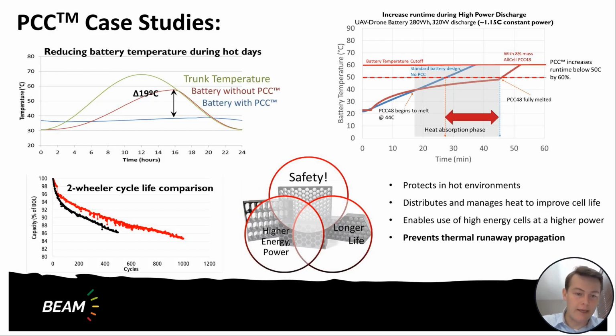We also look at a cycle life improvement of the PCC for a specific two-wheeler application where you'll have high power loads like during regeneration. You'll also have high energy density applications, so you are really pushing these cells throughout its full depth of discharge and full discharge charge voltage profile. So the legend dropped out here, but the PCC battery pack in red was able to achieve greater than 100% improvement in cycle life compared to the non-PCC battery pack. And that's at obviously greater than 80% at the beginning of life capacity.